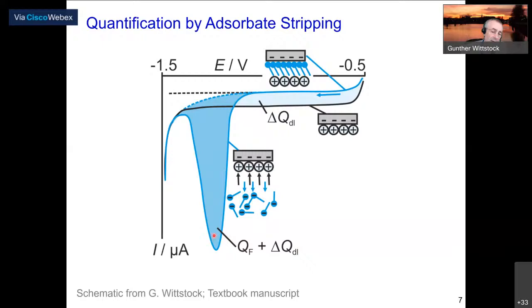And then we oxidize or reduce all the molecules, then the current goes back to the baseline. We can integrate the peak, we get the charge, and then we can calculate further from the charge the amount of molecules contained on the surface, and with knowledge of the area, we get coverages and surface concentrations. However, there's a catch in that procedure, and I would like to highlight that to you.